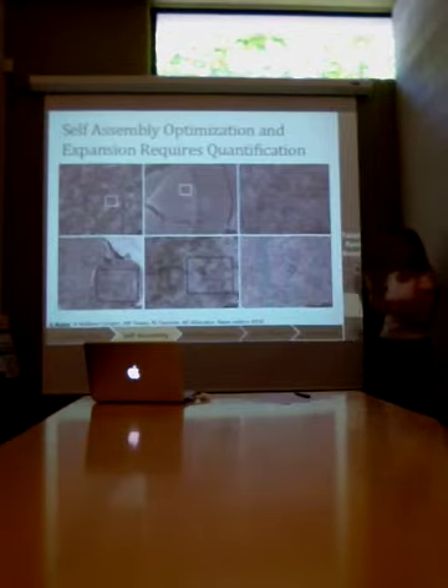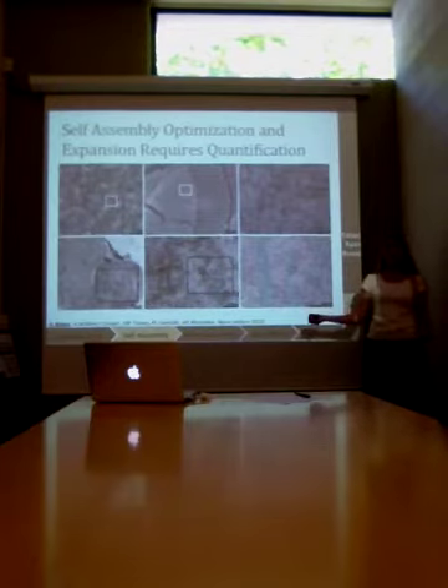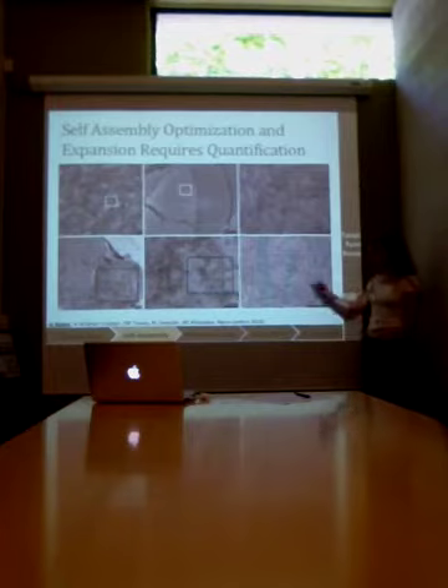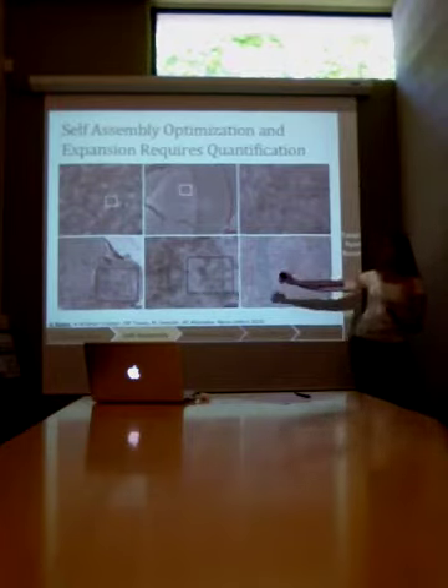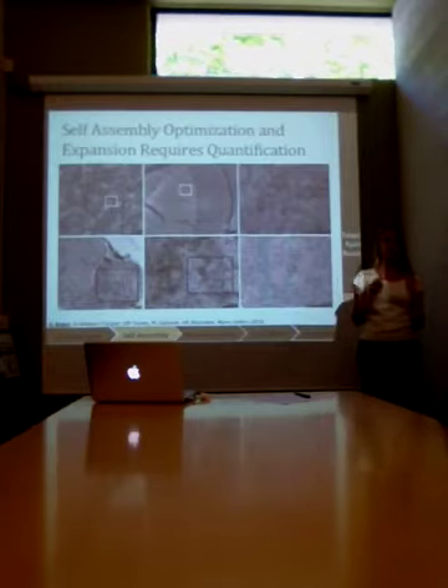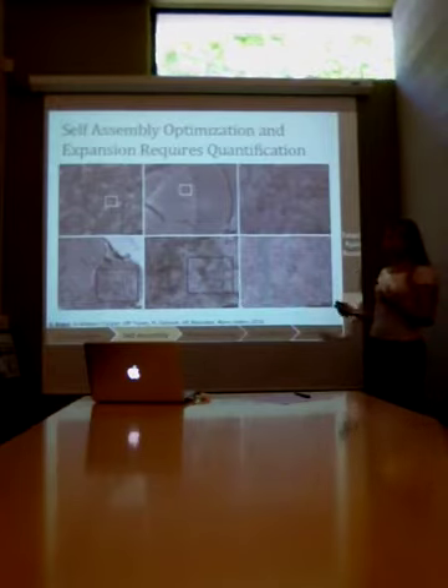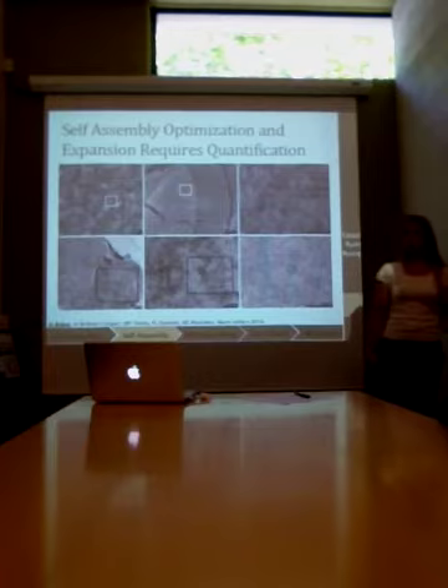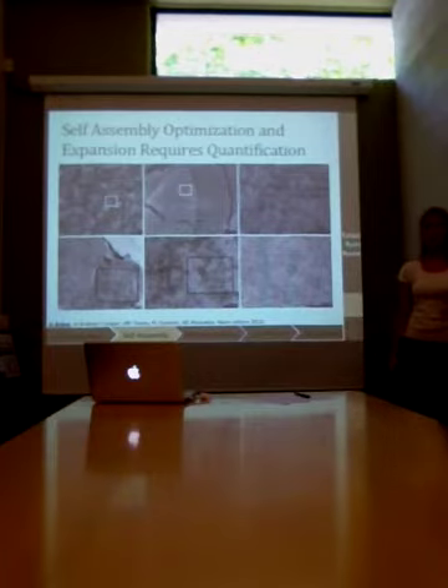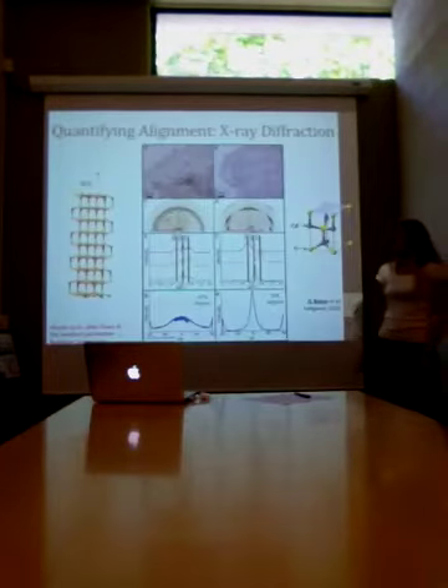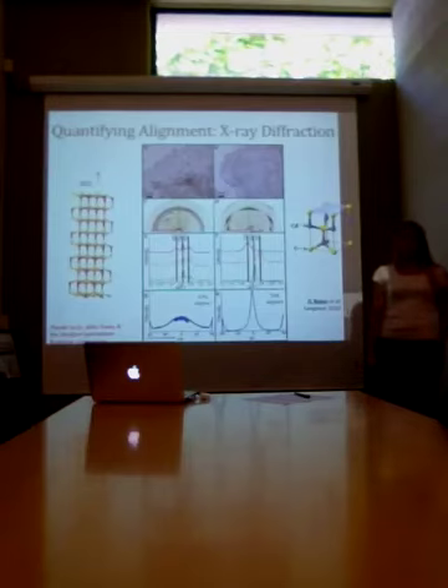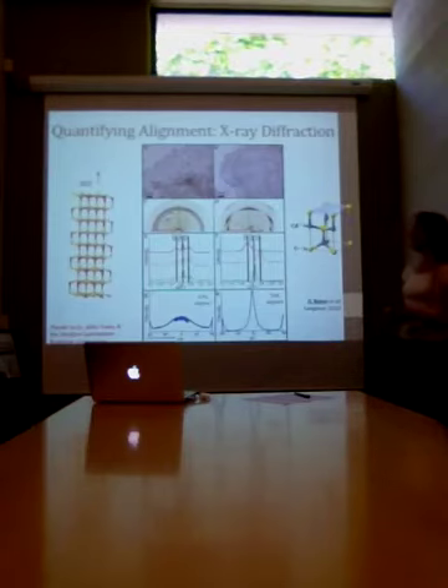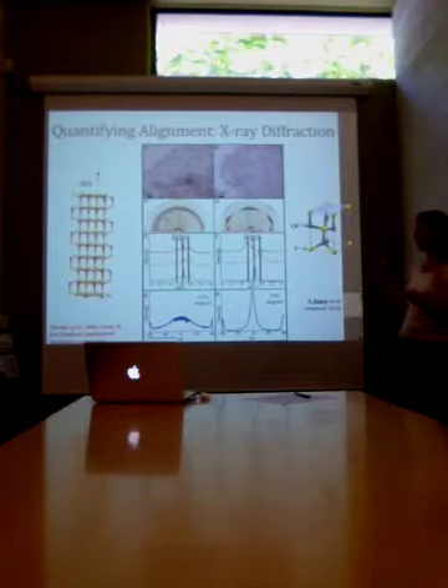and have a little bit of success was that it was really difficult to quantify how much success we were having. Zooming all the way in, we could see, yep, here are 100 or 1,000 nanorods, they're well aligned. But as we began to zoom out, we lost resolution of those individual nanorods. In order to optimize and scale this up, we needed a quantification method that at that time didn't exist. So I collaborated with the Stanford Synchrotron Radiation Laboratory to come up with an X-ray diffraction technique